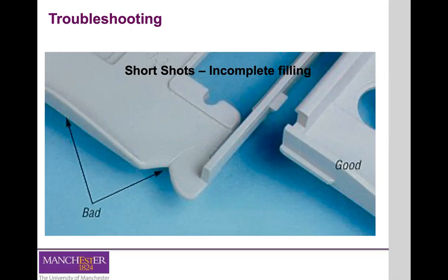And you can do this by increasing the temperature of the fluid you have traveling in your conformal cooling channels. And by doing that, by increasing the temperature, you will maintain the material in a molten state for enough time in order for that material to completely fill in the mold's cavity.